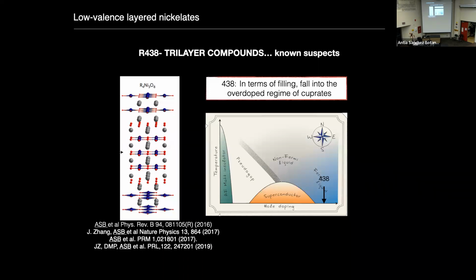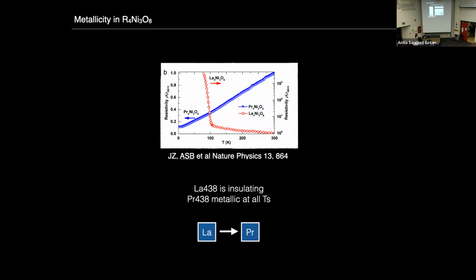So if you remember, but that was way too many slides ago, the tri-layer or 438 nickelates fall into the overdoped regime of the cuprates in terms of electron count, where if we extend our one-to-one analogy, you expect to find a metal. Now, is that what you find? Well, yes and no. You can see here the resistivity versus temperature curves for the lanthanum material that you can see is highly insulating with a transition at around 105 Kelvin towards more of a semiconducting-like regime, but definitely not a metal. The praseodymium counterpart, praseodymium 438, is metallic all the way through, no signature of any transition whatsoever.